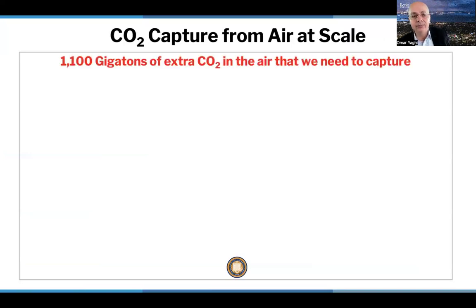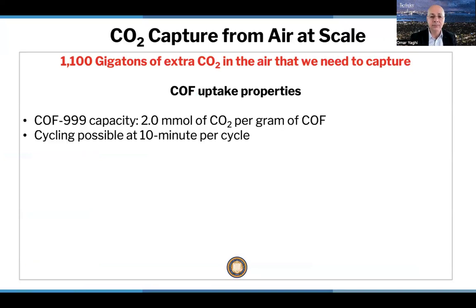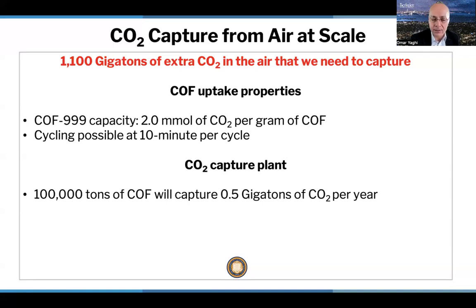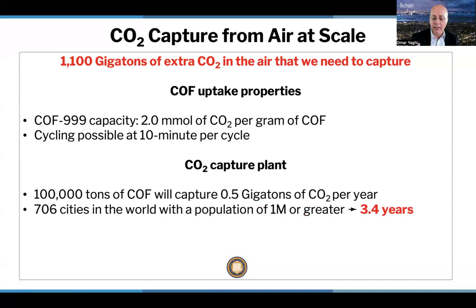Okay, let's now review. We have, as I mentioned, about 1,100 gigatons of extra CO2 in the air that we need to capture. This is the extra CO2 that we put into the air as a result of the industrial revolution. Okay, this is for the last 100 years, we put in that much CO2 into the air. Now, for this COF, even at its capacity of 2 millimole of CO2 per gram of COF, we can cycle about 10 minutes per cycle. Okay, so with these parameters, I can say the following. If I have a plant that employs 100,000 tons of COF, it will capture half a gigaton of CO2 per year. Okay, and if I put such a plant in every city that has a 1 million population or more, that's about 700 cities around the world, it's going to take us less than 3.5 years to take that CO2 out of the air.